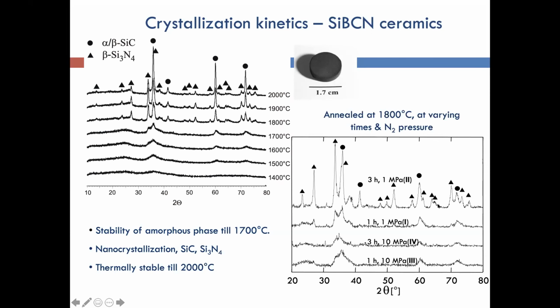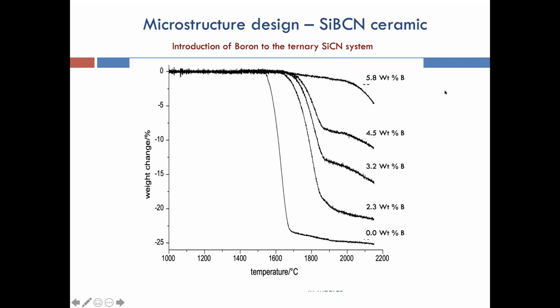I also wanted to let you know that the crystallization is strongly affected by the nitrogen partial pressure. As you see here, crystallization is resisted at higher nitrogen partial pressure. But that may not be technologically very relevant. What is technologically relevant is that it is possible to keep the material quite stable at extremely high temperatures, which can be useful for certain aerospace applications.